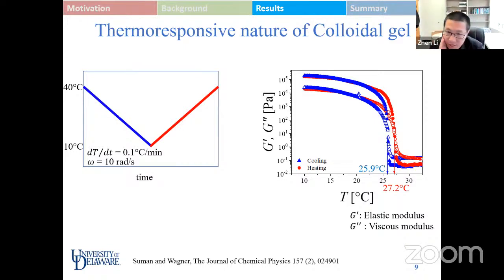Yeah. So as my understanding, it's the local relaxation. There's a local relaxation time for the local structure to relax to a new state, right? Yeah. So for high temperature, it's different with the local structure for that. So this is the kind of material memory, right? So it's a history dependent process. It's not just the transient state that determines how it evolves.